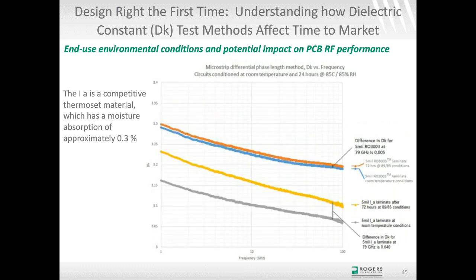This is the same testing, except now I'm looking at phase response and extracting the dielectric constant on the y-axis, with frequency on the x-axis. The difference in dielectric constant between room temperature testing and the circuits being conditioned 3 days at 85-85 for the RO3003 materials is 0.005. In the case of the competitive PPE-based thermoset materials at 79 gigahertz, the difference in dielectric constant is about eight times the difference, 0.04. So moisture absorption can be a pretty big deal.